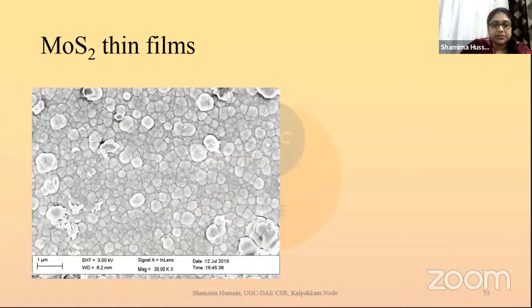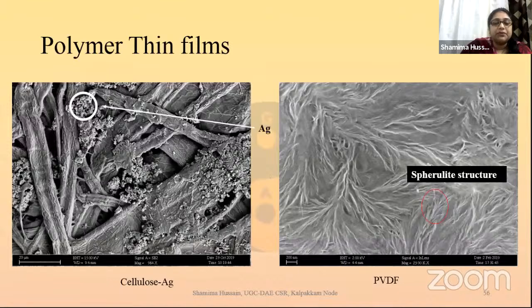These are some of our own results. MoS2 thin films, they look like this. This is a polymer thin film. This is the first part. This is a cellulose film with silver on it. These are the silver nanoparticles which we have seen with EDAX, and they're silver. Cellulose things we can see as I was talking. This is what you got.